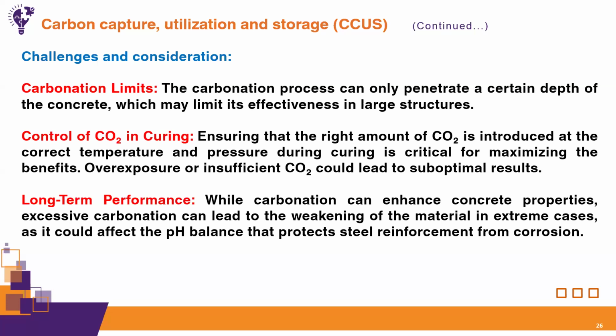And finally, the long-term performance. While carbonation can enhance concrete properties, excessive carbonation can lead to the weakening of the material in extreme cases. So what will happen actually if we add more carbon? Ca(OH)2 will be utilized, and this Ca(OH)2 is responsible for the high pH of the concrete, and this high pH helps in protecting the steel reinforcement from corrosion. So if more Ca(OH)2 is utilized because of carbon curing or carbon addition, the pH of the concrete will be low and your concrete will be exposed to corrosion. So that's why it is very important to evaluate the long-term performance of both these techniques so that there should be no corrosion related issues with steel reinforcement.